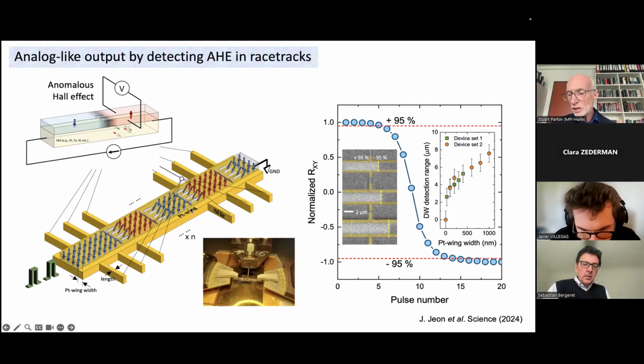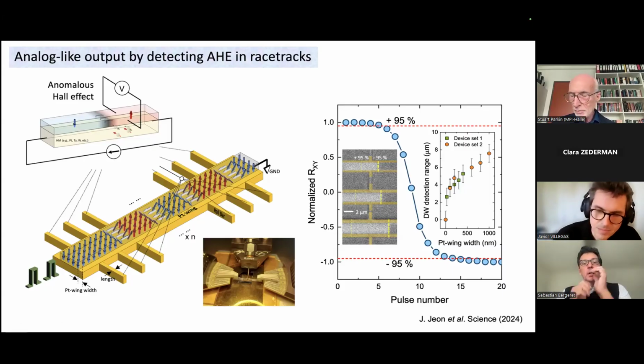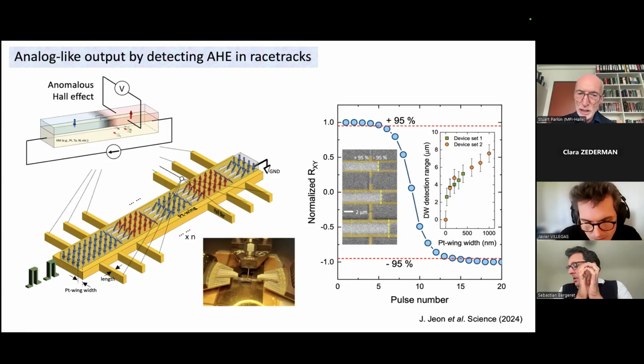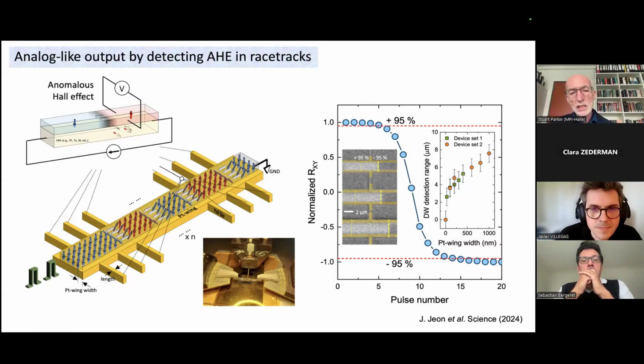And we demonstrated by experiment and by simulations that, depending upon the width of that platinum wing, we can detect the magnetization away from the position of the Hall bars, these electrodes, which you can see. And along one racetrack, we have a whole series of these Hall bars, allowing us to detect a domain wall as it moves along the racetrack. And by designing the width of this platinum wing, we can design the Hall bars so that we can detect a domain wall anywhere along the racetrack.